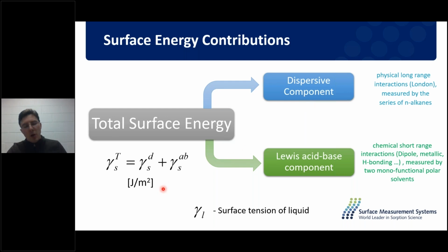We can also inject polar probes, so something like dichloromethane, toluene, ethyl acetate, these molecules that have permanent dipoles. And we can use these to calculate the influence our surface has as a result of polarity. So how much ionic species are on the surface? How many polar functional groups are on the surface that are contributing to those dipoles that are going to be causing strong interaction with our polar probes. Now I can add together these two different energies, these two different energy profiles, to get my total surface energy. So I can split my energy into three different areas and analyze them, and I can analyze them separately using this technique.